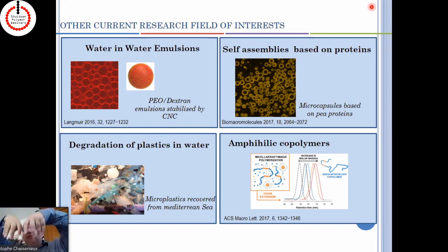But now, if you have a comb, you must have more than one block to extract from the core of the hydrophobic reticulation nodes of your system to relax the strain. So the relaxation times with grafted systems are bigger than the relaxation time that you measure for pure tri-block copolymer. But the pH dependence has exactly the same shape.